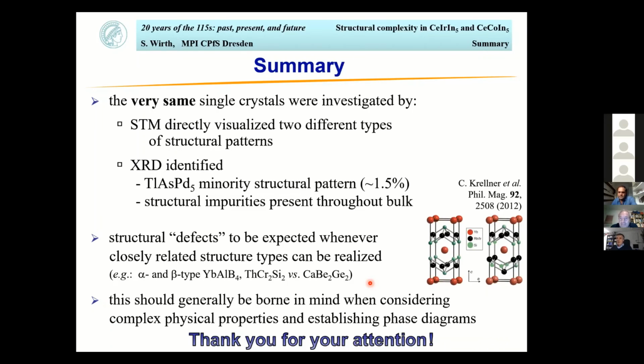Well, I wouldn't put any emphasis on these numbers. I would actually argue this is just a coincidence. At least I don't have any indication, or I wouldn't know why. I think it just worked out that way for these materials, or for the samples we looked at. As I mentioned, in principle, you should look at each and every sample, or at least at each and every batch, to pin that number down. But it's actually pretty cumbersome, even for the XRD. So we didn't do that.